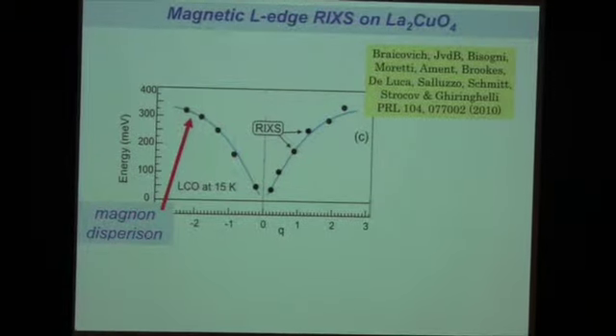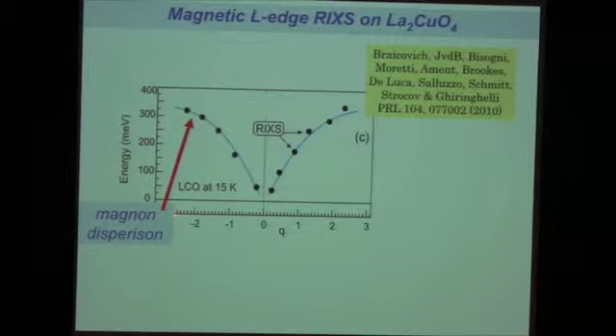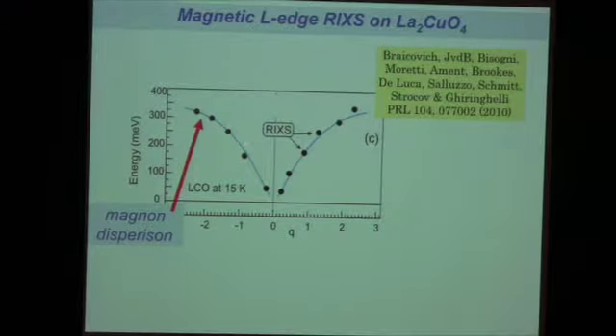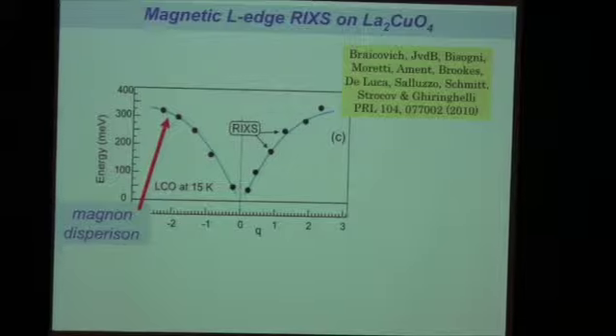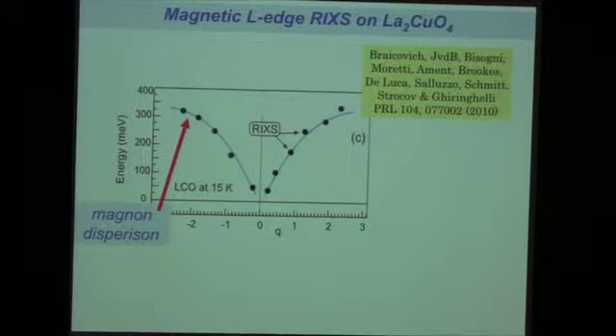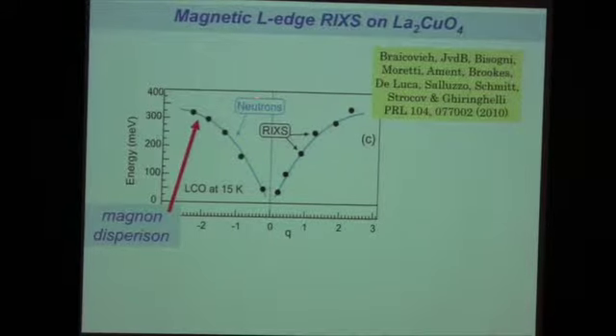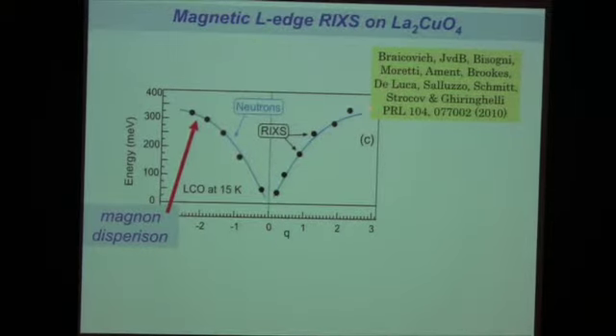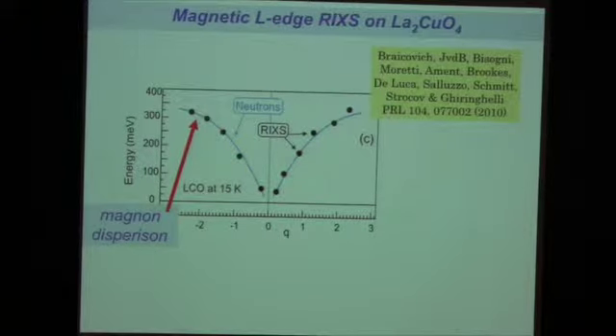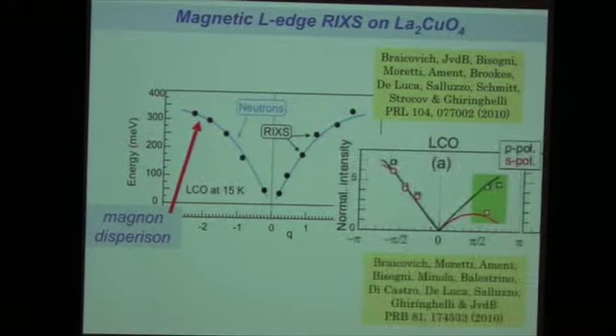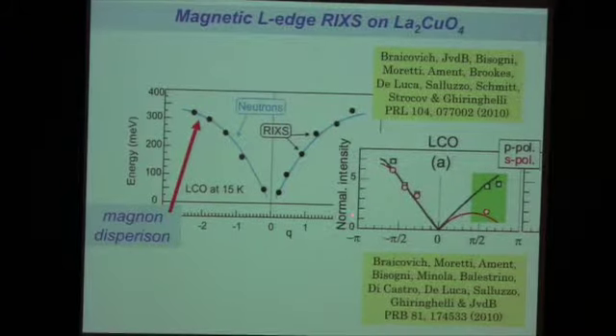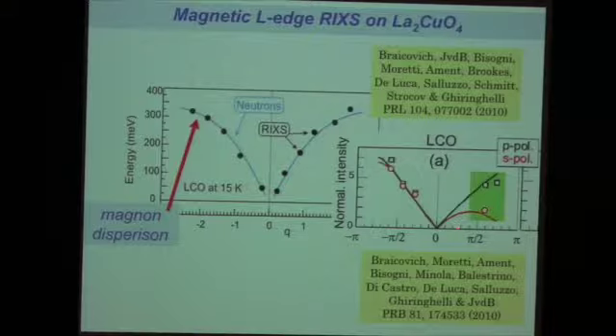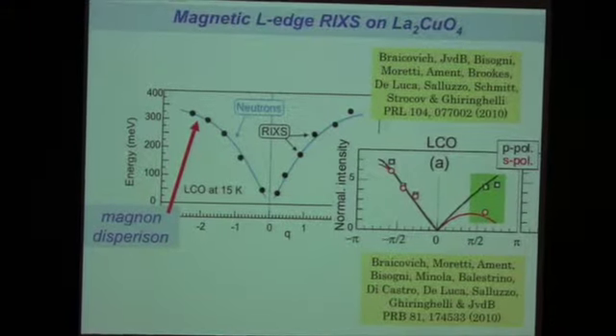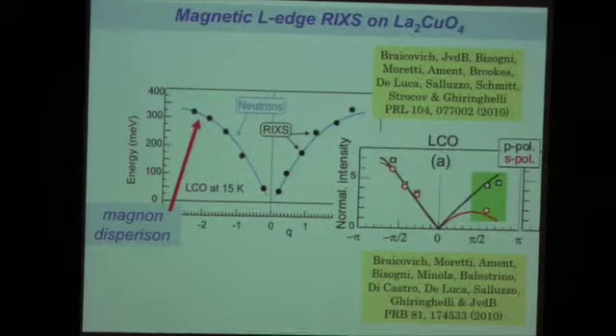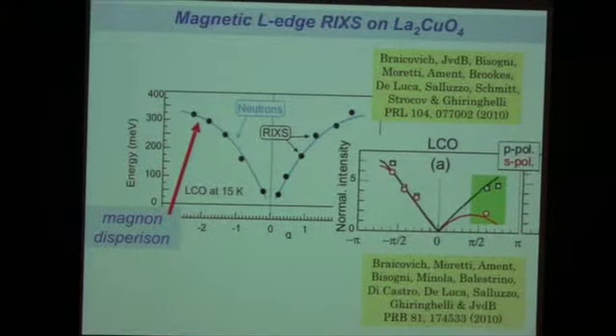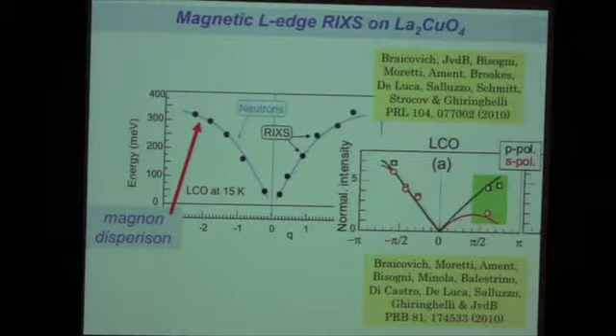This is the magnon dispersion as measured by RIXS. So this is momentum, this is energy. The dots are the RIXS data that I've shown you before. And the blue lines actually are not fits to the data, but the blue lines are the results of neutron scattering. And you see they're perfectly nicely on top of each other. And we understand not only the energies, this is here, this is the intensity. We have also calculated the theory for the intensity, the RIXS intensity of the magnon excitations, which also compares well to the experiments, where intensities are much more difficult to calculate than energies. So this is really nice.